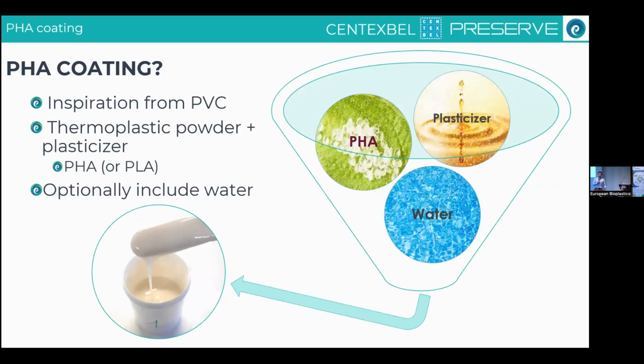The issue, however, is how do we turn this PHA powder or pellets into an actual nice and homogeneous barrier coating? For this, we took inspiration from the PVC sector, where they use something called a plastisol. They mix a thermoplastic powder and a plasticizer, they heat it, the plasticizer is absorbed by the thermoplastic powder and it gels into a homogeneous coating. So we tried the same approach. It worked for PLA, it works for PHA, and optionally we sometimes include some water and processing additives to make sure that the coating behavior and the flow of these materials is what is needed.